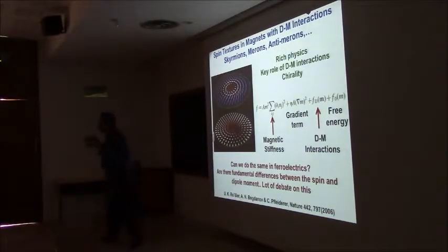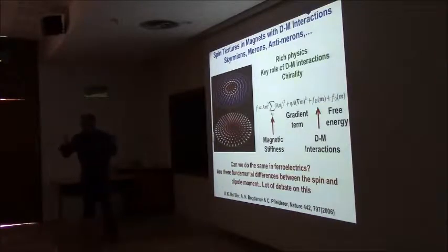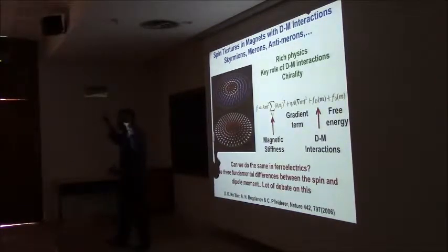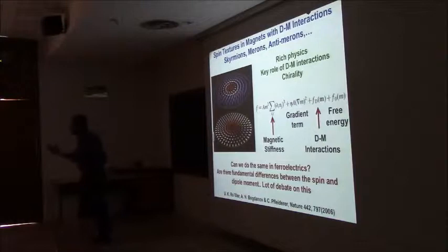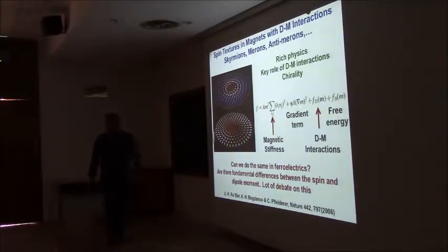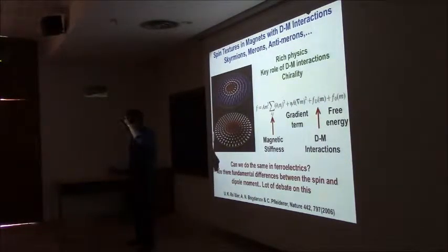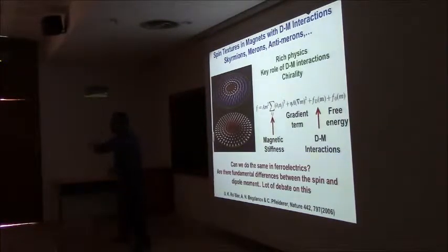In the case of ferroelectrics, like lead titanate, people always believed that it went through the so-called Vanderbilt mechanism. David Vanderbilt proposed this in the 1990s. The idea was, if this is my dipole pointing up, and on this side it's pointing down, it didn't rotate the dipole because I have a huge penalty from anisotropy. Instead, what it did was to reduce the magnitude of the dipole. I have that flexibility to keep on changing the magnitude. And then it goes to zero, goes to the parent phase, the high temperature phase, and then it switches the direction of the polarization.